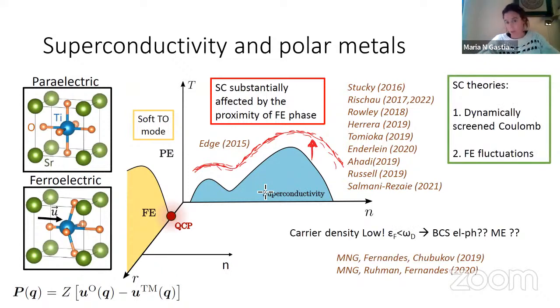because this is somehow an indirect indication that these fluctuations might be important. Something that I would like to point out before going on is the fact that these are extremely low carrier density systems, so their Fermi energies are around 5 meV, 10 meV, 15 meV, and so on. That places them in an energy regime where the Fermi energy is much, much smaller than the Debye frequencies, the characteristic phonon frequencies that one usually looks into to apply the conventional electron-phonon superconducting pairing formulation. All the tools that we have are controlled in the limit where the Fermi energy is the large energy scale compared to the phonon degrees of freedom. So you have the picture of a fast electron and a slow lattice vibration, but this is not the case here.